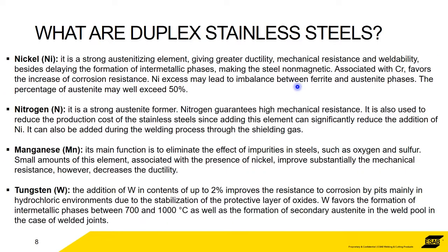Nickel's a very strong austenitizer. It wants to create austenite out of the ferrite. That's what it does. When the alloy is liquid in a molten phase, it's ferritic. As it's cooling down, you have nickel in there, and the nickel will cause the austenite to form. Obviously you can have too much in there. You can get the balance wrong between ferrite and austenite, so that's where you need to be careful.